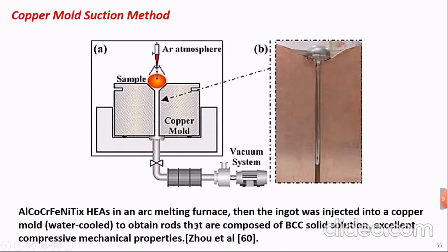One of the well-known methods is the copper mold suction method. In this method, after we melt in arc or induction, we pour into a water-cooled copper mold to control the cooling rate. At that time, we can control the temperature of the water that cools the mold and obtain the structure, of course, based on the cooling rate.